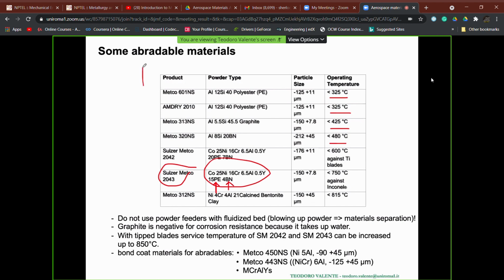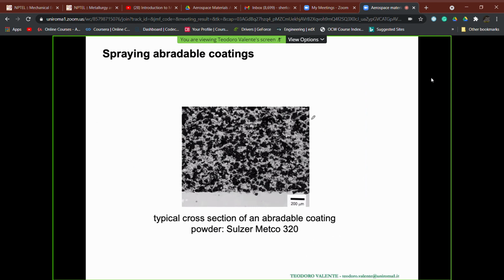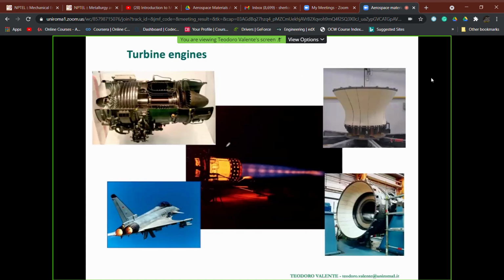And this kind of coatings, in which we can also have ceramic phases, usually are made by plasma. And this is one example of an abradable coating, and you see all the black parts, which are the mixture of the polymer-based materials and the ceramic materials. And so the spraying and fabrication of abradable coatings, which are the standard solution for high-performing engines, is another field in which plasma spray technology is widely used. And so we are again inside the area of the engines in our aircraft.